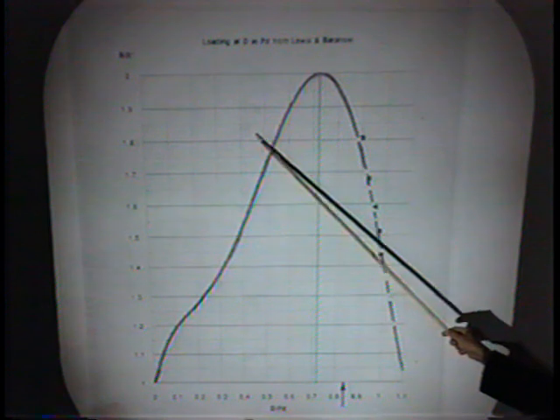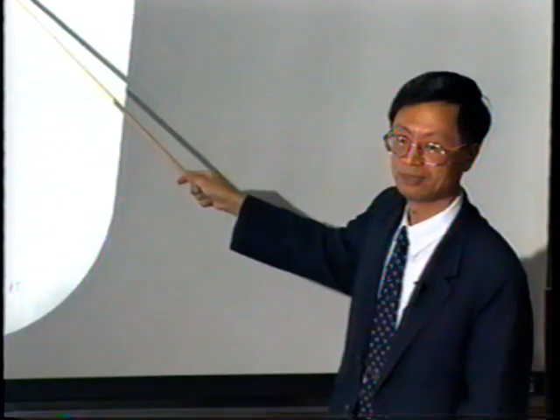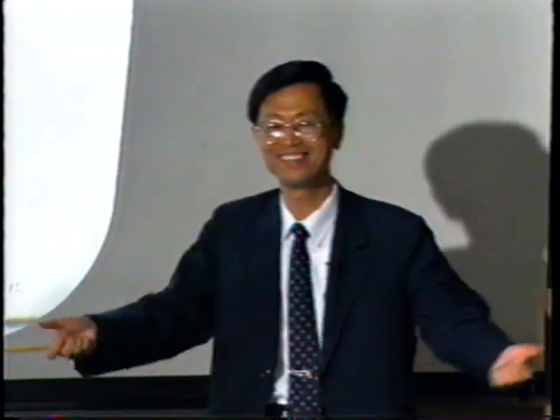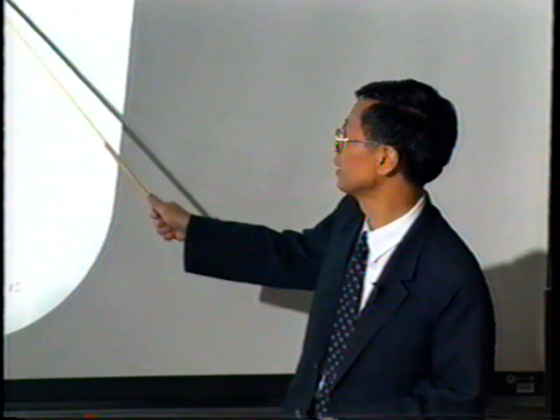Then third, finally, when we reach this part, we take out the sample and weigh it. Previously, we thought when we take it out, the gas will leave very quickly, so we have no time to wait. But in fact, it's not so quick. We still have enough time to weigh it. And the weight proved that we are on the other side.